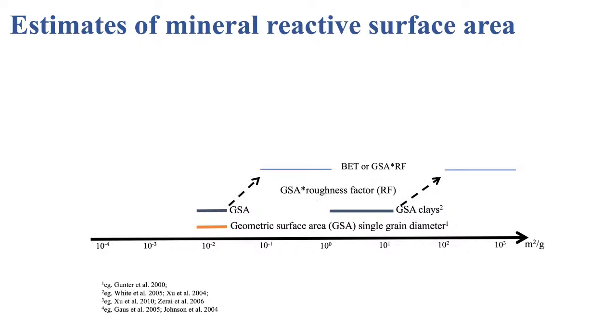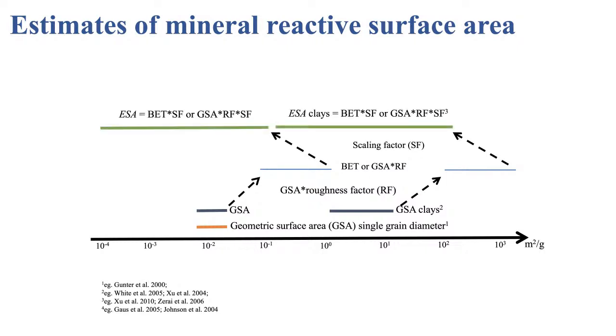This rough surface area or specific surface area, you can also get in the laboratory from doing a BET measurement. Now, we've also seen evidence that potentially only some sites on the surface are actually going to be reactive. We can account for this by applying a scaling factor. This is somewhere between 1 to 3 orders of magnitude, where the modeler just picks the value that they want to use. There's really little guidance on what value you should be using. And sometimes the scaling factor is applied directly to the geometric surface area.